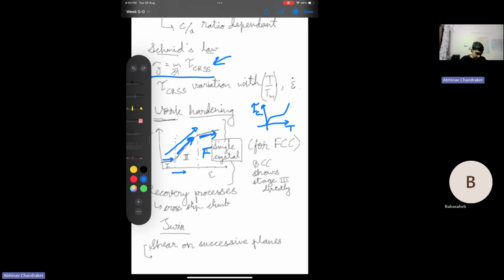And at high temperatures, these recovery processes will be slightly different and they will be much stronger because you have more thermal energy available for annihilation as well as formation of different structures. Diffusion is easier, so that will also lead to the climb mechanism getting activated. So edge dislocations can also overcome obstacles more easily by climbing to a different slip plane.